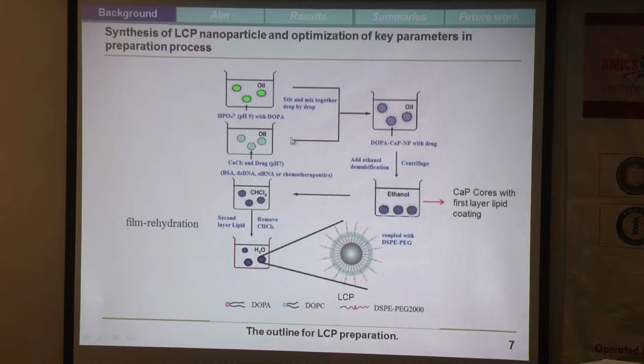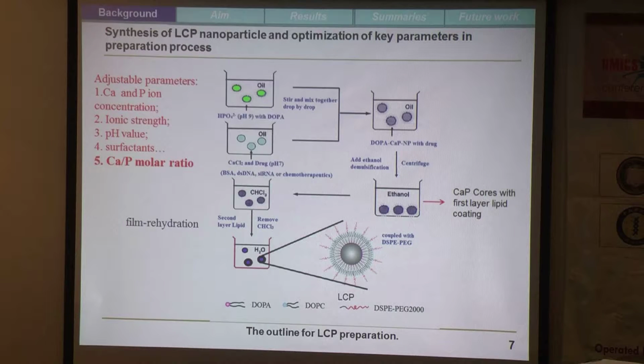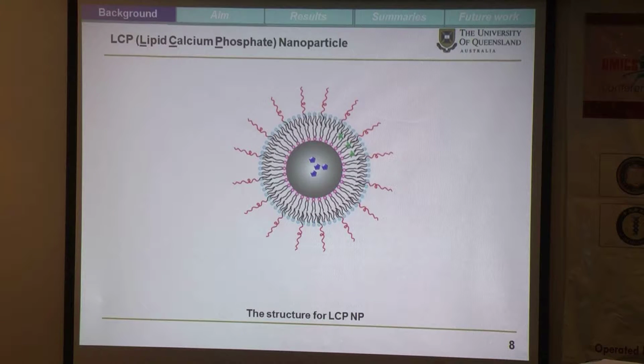Although the preparation process of the LCP nanoparticle seems pretty simple, the formation of the precipitation of calcium phosphate has been described as a fairly complicated process dependent on several parameters such as calcium and phosphate ion concentration, ionic strength, pH value, and the nature and the concentration of the surfactants. The calcium to phosphate molar ratio is also very important because the ratio may initiate different kinetics of the reaction and result in precipitations with different properties. So how will the calcium to phosphate ratio influence the properties of the LCP nanoparticles?